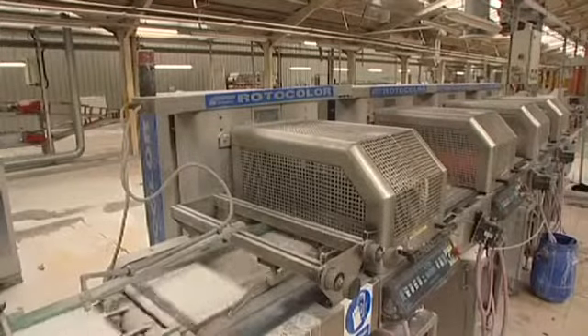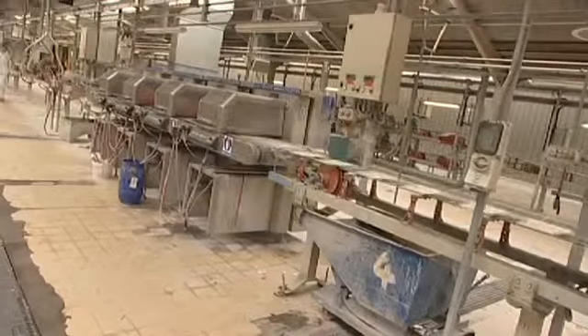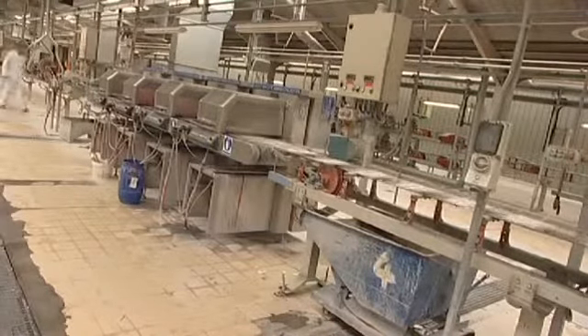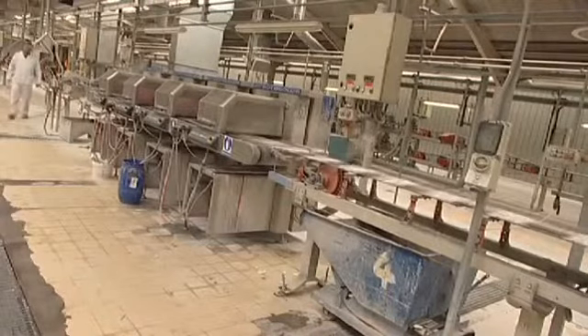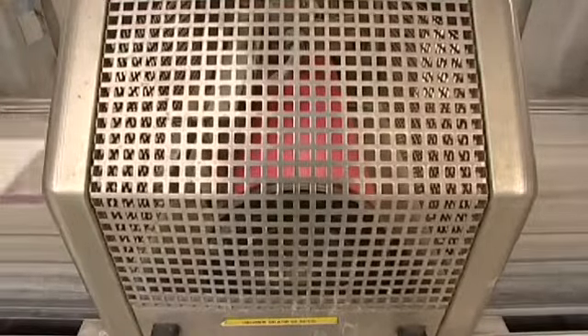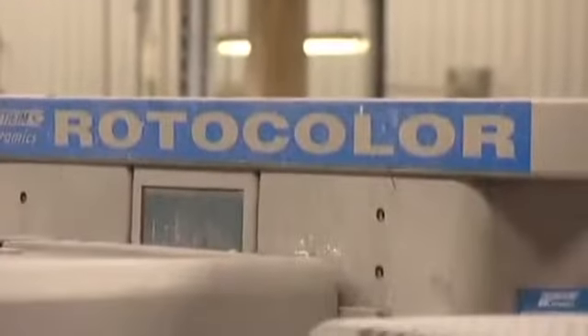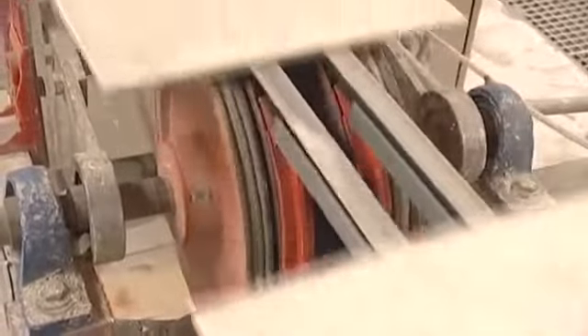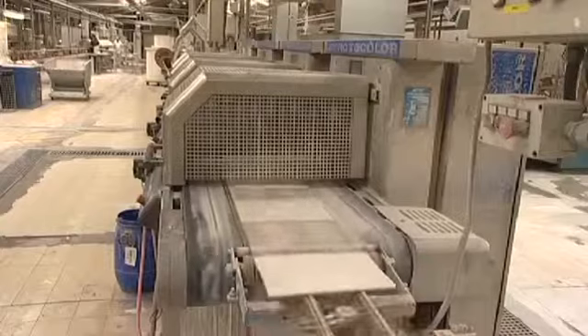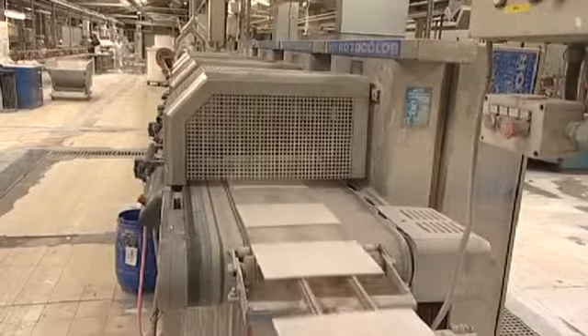Tiles can be decorated using one of several processes. The traditional method for volume production was silk screen, which allowed designs using up to 6 colours to be applied. During the 1990s, a new method of decoration was developed which used neoprene. This material has the design laser etched into the neoprene, which is formed into a roller. Using one roller for each colour, it transfers the print colour onto the tiles. This new process, called rotocolor, has the advantage over silk screen when the design is a stone or marbled pattern needing random decoration, rather than every tile being identical.